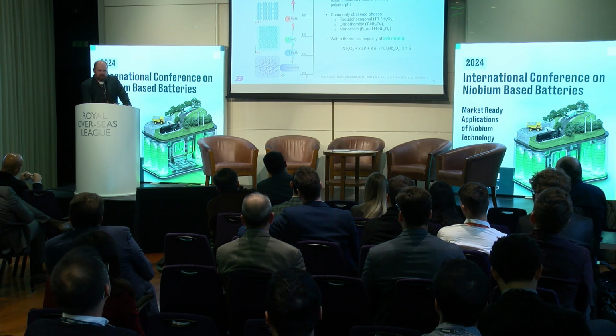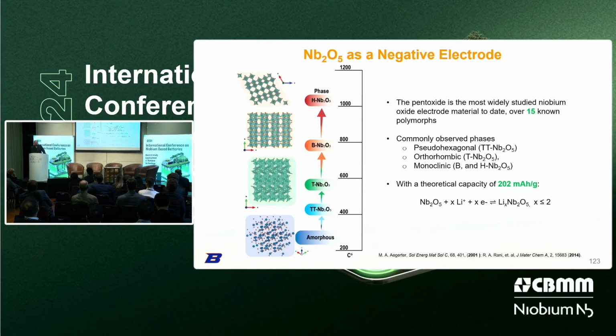Does it have to be lithium insertion? I don't know. I think that's a question that can be answered more. I think there are more than just lithiation that can cause unique crystalline structures to form. In this case, rock salt might be the only one that can be done with lithium. As we push that lithium in, we're causing the niobium to develop what I believe is a gradient in the material, which then eventually the niobium's like, I don't like this structure. I'm going to tweak a little bit to allow the lithium to come in, and then it's metastable enough that it's not going to revert back to the amorphous. So that's why it has to be below that line that I showed.